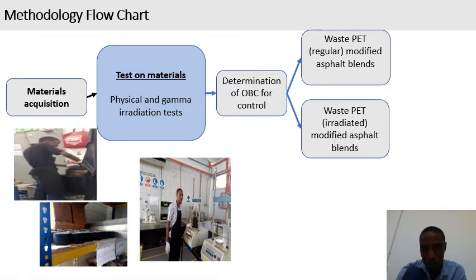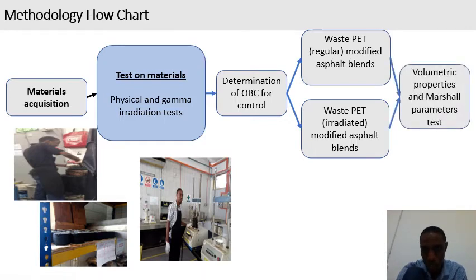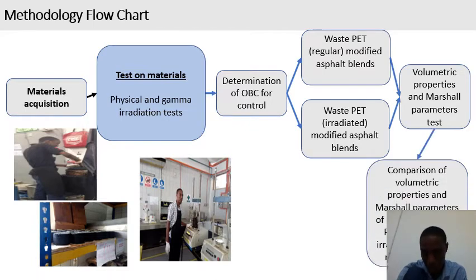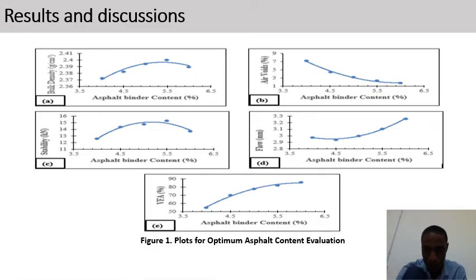Then we have two types of modified mixtures, one containing regular PET and the other containing irradiated waste polyethylene terephthalate. After which the volumetric properties and Marshall parameters tests will be conducted, and then a comparison of these volumetric properties of three mixtures, that's the control, regular waste PET modified mixture, and irradiated waste PET modified mixture, will be carried out, and then based on the comparison, conclusions are made.